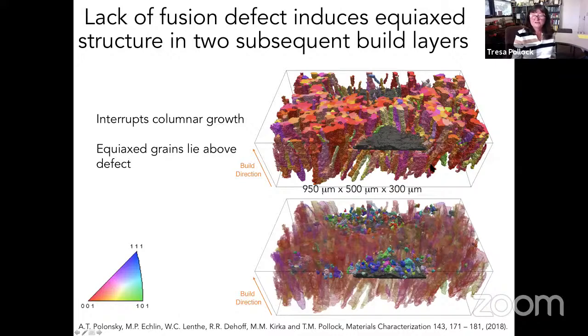And so if you take the 3D data set and look at this lack of fusion defect, you can clearly see the size of it here. But what you learn from looking at the 3D data is that, okay, there's some disturbance in the build process, and that results in lack of fusion and a void here, but that defect actually extends well beyond the moment where it was created because it requires grains to renucleate as equiaxed grains in this background of columnar structure.